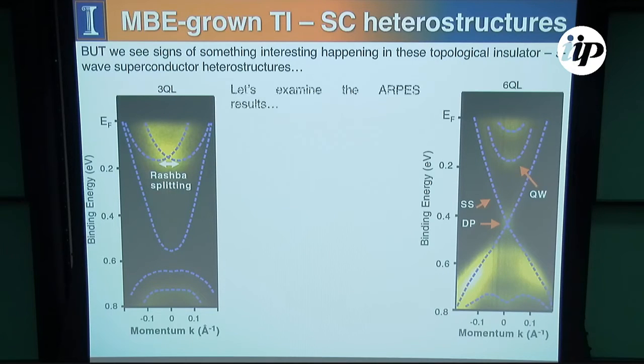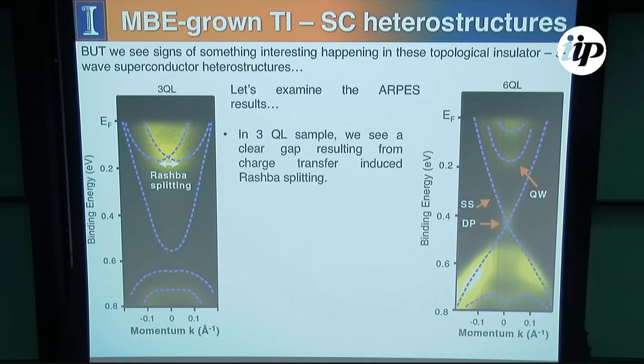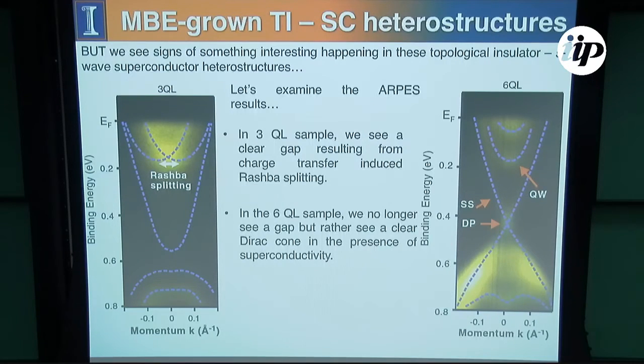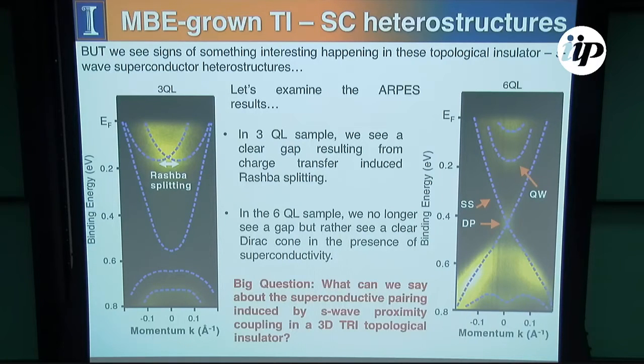And the interesting thing about this system is in the quintuple layer system, we also see Rashba splitting. So this Rashba splitting comes from the fact that when somebody else grew the bismuth layer, there's a charge transfer in between the bismuth and the topological insulator. And so what this does is it creates an electric field, and the electric field increases the Rashba splitting. And so you get this interesting effect here. So other things in the 6 quintuple layer system, obviously, as I mentioned, there's no hybridization gap. And the big question was, okay, if you can grow these systems now, what would we expect to see?